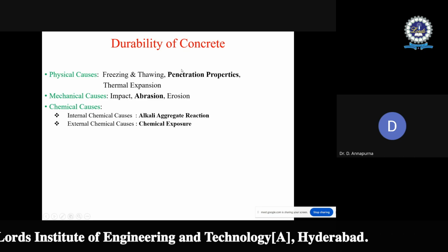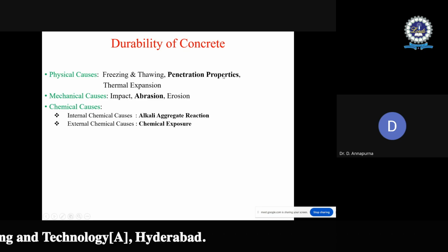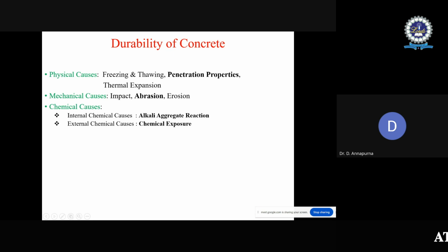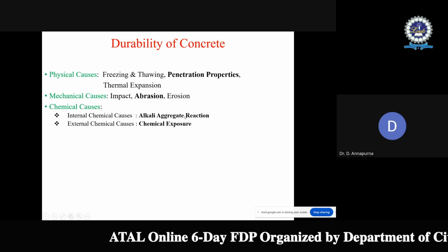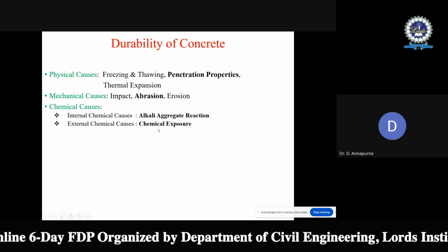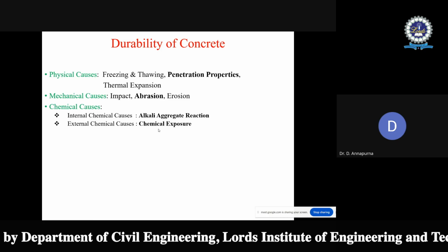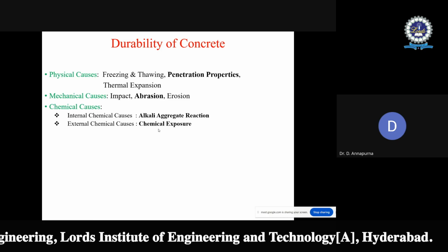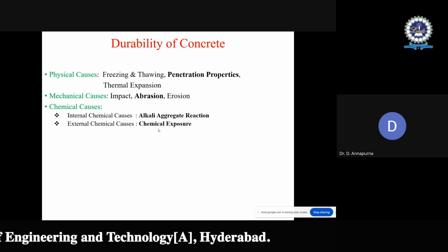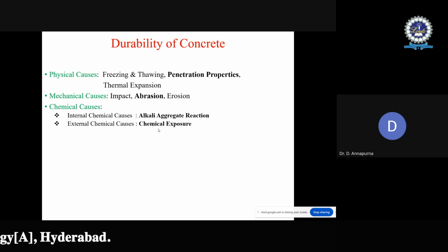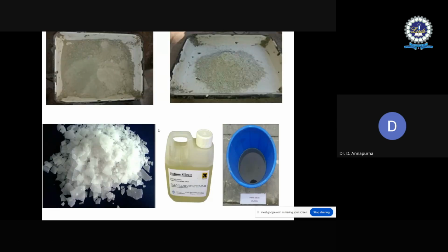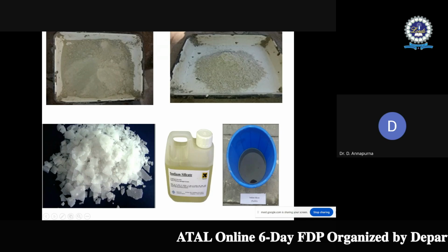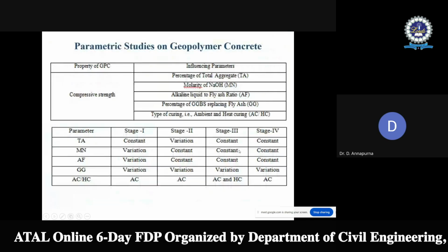So here in this particular study, all the penetration properties are identified. Then under the mechanical cause, abrasion test is conducted on the geopolymer concrete. Then alkali aggregate reaction test is conducted. Then the chemical exposure, like sodium, sulfate, acid, and chloride exposures are conducted on the proposed geopolymer concrete. The materials used here are fly ash, GGBS, then sodium hydroxide and sodium silicate solution.